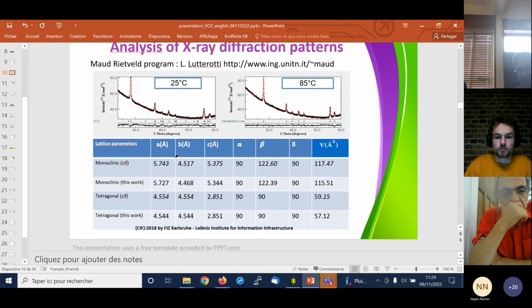Yeah. So basically, when you put some tungsten into the VO2, you are going to modify the environment of the vanadium oxygen atoms. And basically, what's happening is that once you put tungsten inside, you change the band energy levels of the doped material. And if you put too much tungsten, by changing the environment of the vanadium atoms, which are substituted by the tungsten, you end up with something which becomes metallic. So you really change the distances between vanadium and oxygen, and this change in distances is typically one of the reasons for which you get some transition in vanadium dioxide.